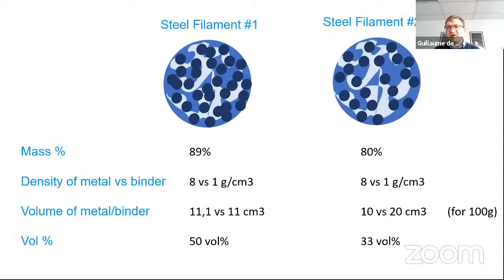To give you an example, here are two filaments that you could find on the market. If we talk in mass, one of them has 89% of metal and the other one has 80. You could say, well, the difference is not so much. It's very close, 80 to 89. That seems similar. If you calculate it in volume% with the density of the metal, which is 8 times bigger than the binder, you will find out that actually this is a huge difference.